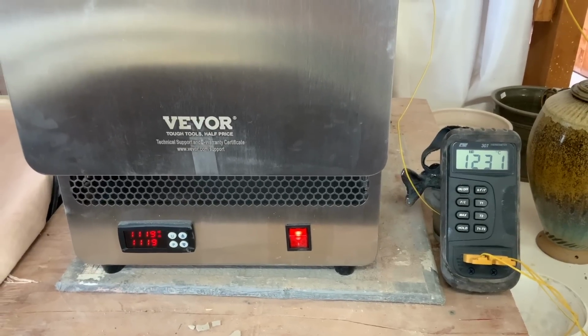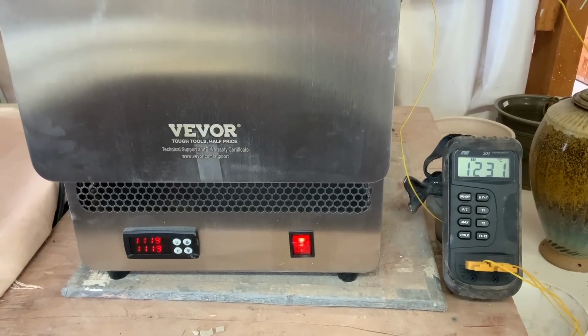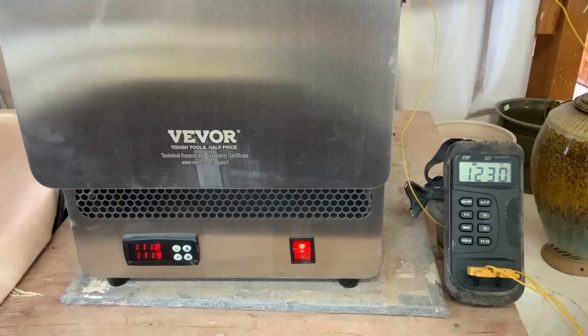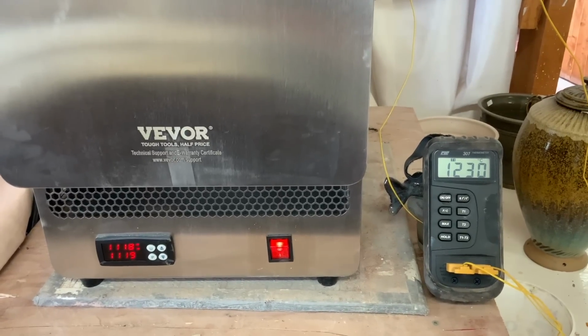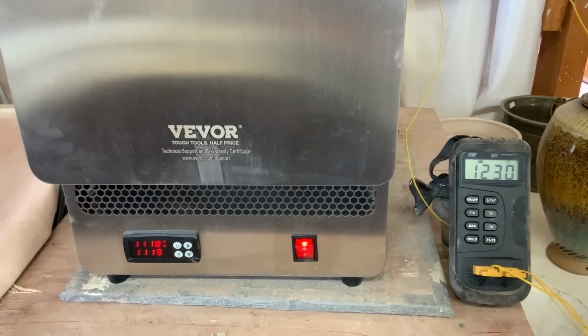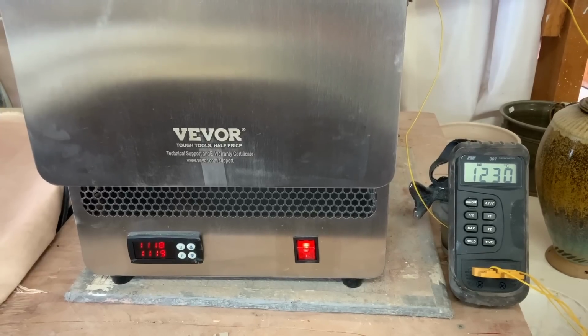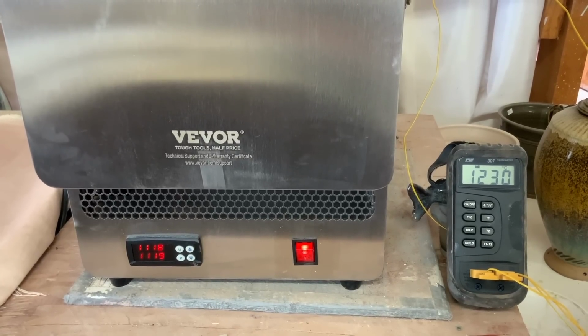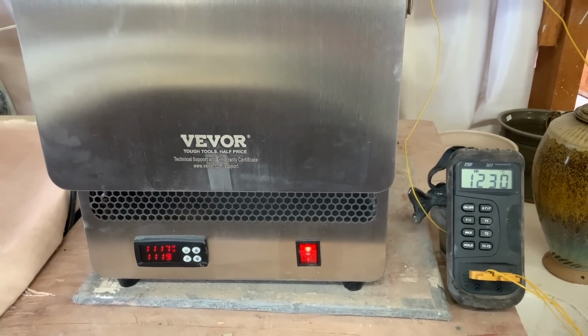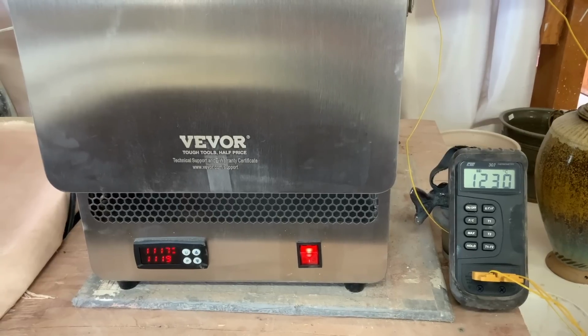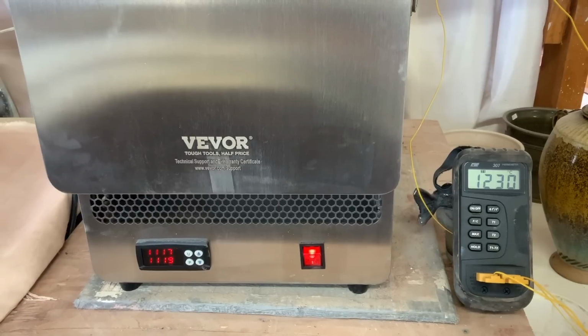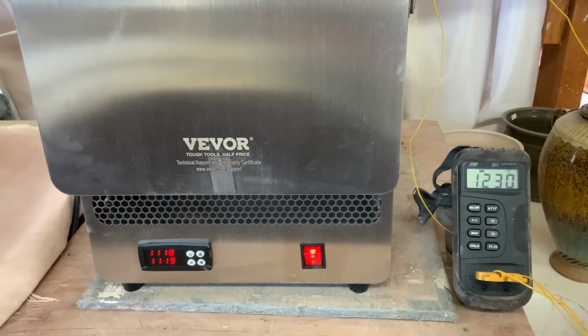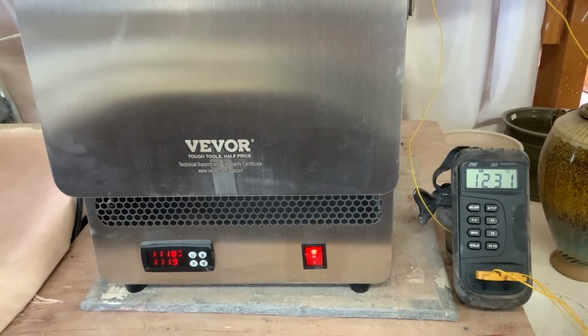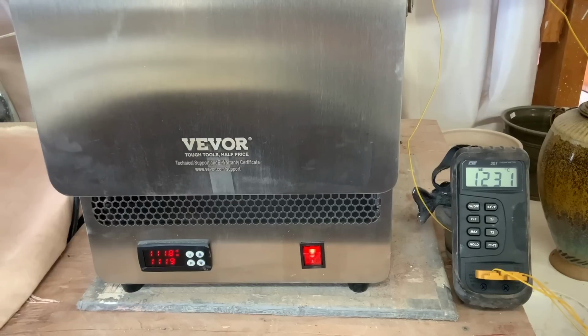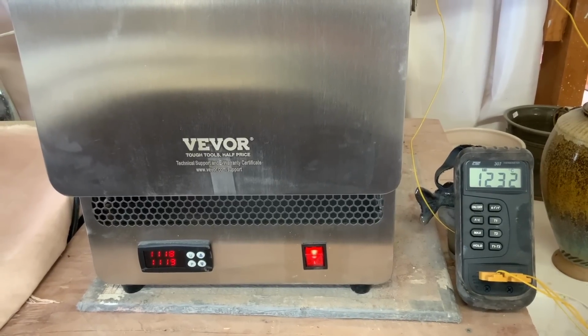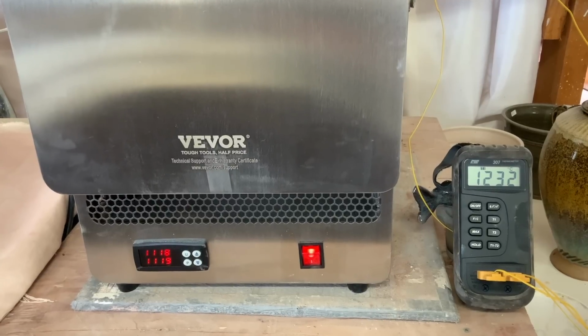Okay, the kiln is now at 1119 with the Vevor thermocouple, and my pyrometer is reading 1230 to 1232. It's fluctuating a little bit, and so we know that a true cone 6, which is 1232 at 108 degrees an hour normally, but this thing goes up 1,000 degrees an hour, so I can say 1119 on the Vevor kiln is equal to 1232 on this thermocouple that I own, which I know is pretty accurate.